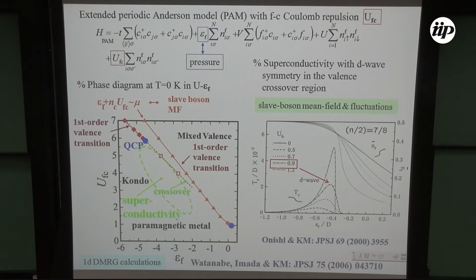By treating this with slave boson mean field approximation, we obtain the change of the f electron number as a function of the level epsilon f. Effective pressure increases epsilon f, so as we increase the pressure, nf changes gradually if U_fc is 0. But increasing U_fc, this changes sharper and ends up at the first order critical point.